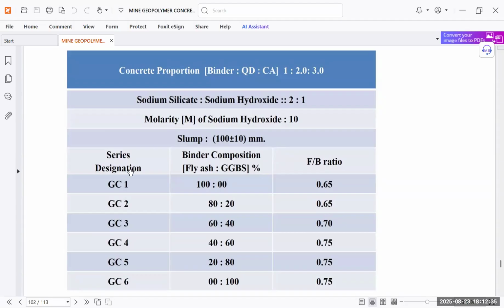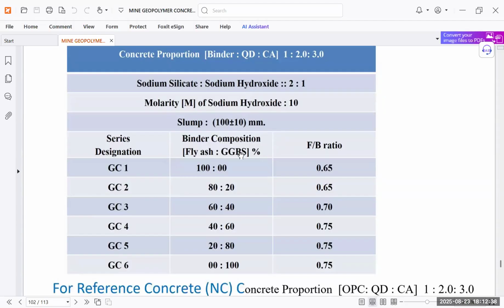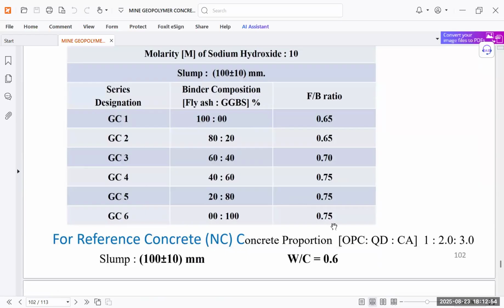And for the series designation, we have taken different fly ash to GGBS ratios: 100 to 0 is GC1 and GC2 is 80 to 20 ratio. So we can see that, as per the different requirements of the work, we can vary this binder composition and change the fluid to binder ratio so that we can get the desired result.